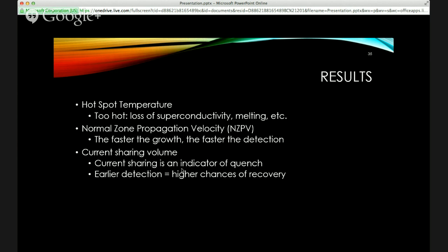And then also something new was the current sharing volume. Current sharing is what happens when, in normal operation, all the current flows through all the conductors. However, when you have a quench, the current will divert to other layers. In this case, I have the heater and the middle conductor. When a quench starts, the current will divert to the conductor either above or below it. But more often than not, you'll see the change faster in the conductor above it just because of the geometry. So the current sharing is kind of a precursor, but it can give you a false positive because sometimes things can recover. It depends on what kind of chances you want to take. With earlier detection, you have a higher chance of actually recovering, so that you avoid the burnout we saw before.